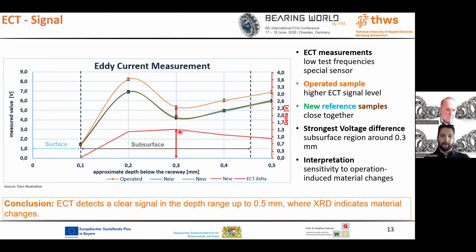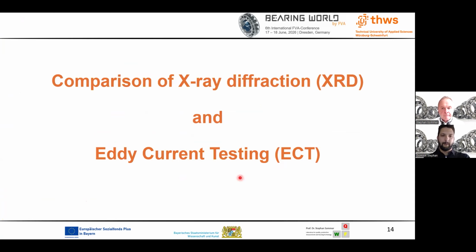This is important because this depth range is also relevant for rolling contact fatigue and is supported by the destructive X-ray reference measurements. So the key message of this slide is, eddy current detects a clear signal in the depth range up to 0.5 millimeters, where X-ray indicates material changes. After looking at the eddy current signal alone, the next step is to compare it with the destructive X-ray reference data.